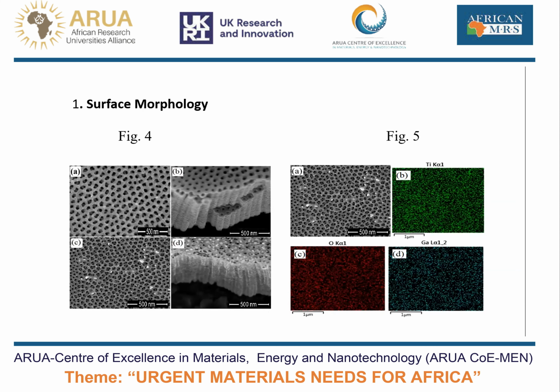Surface morphology analysis. Figure 4 shows the surface morphology of the prepared titanium oxide nanotube films. Figure 4B and 4D show the lateral view of the obtained titanium oxide nanotube films. It can be seen from figure 4C and 4D that some small white particles are seen on the surface of the nanotubes, which is the gallium oxide that was decorated on the surface.